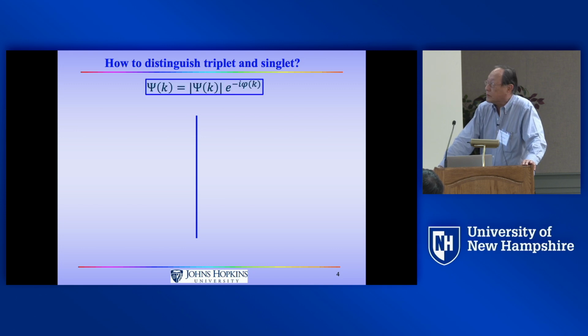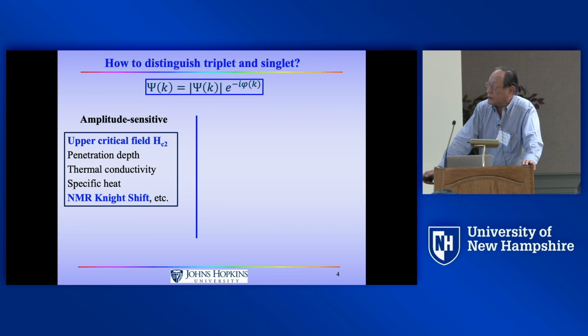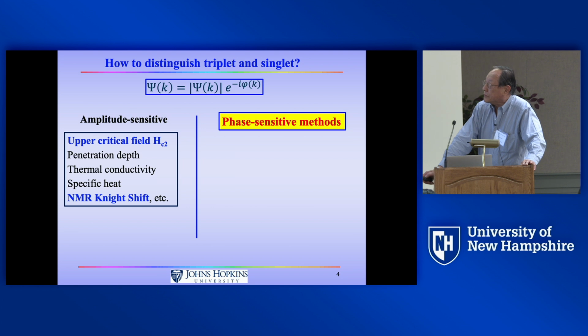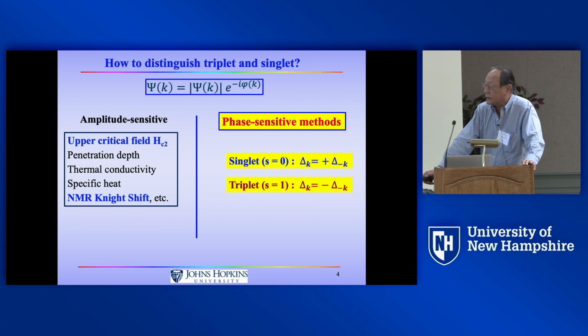How to distinguish a triplet superconductor? We all know the superconductor has a wave function; there's the magnitude, and it also has the phase. Most of the time, people use amplitude-sensitive methods. These are the methods people have used over the years, decades before. The most common ones are upper critical field and the NMR Knight shift. And the phase-sensitive methods involve trying to address the question of whether the gap has even or odd parity, or whether one can measure the Cooper pair spin, or measure time reversal symmetry. So now we ask the question, which triplets can we ascertain?